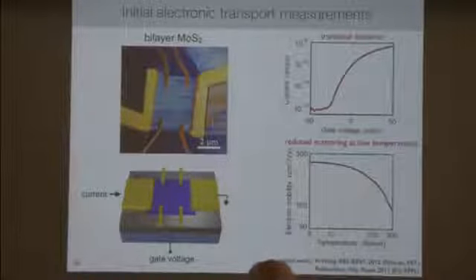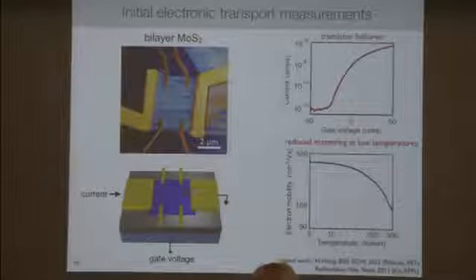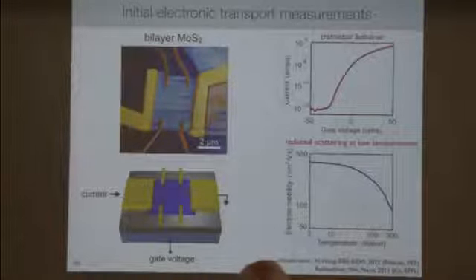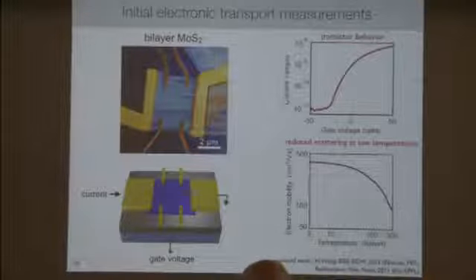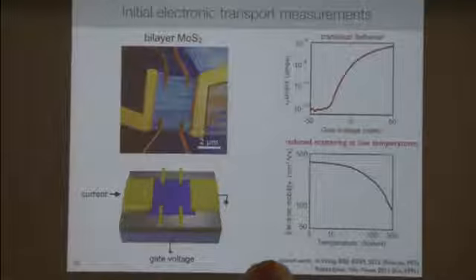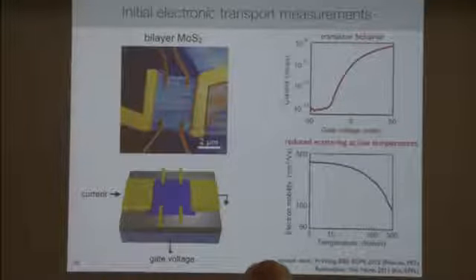So we've done some initial measurements on these materials. So here's a bilayer of molybdenum disulfide that we've contacted with gold, and we can measure then current flowing through the molybdenum disulfide as a function of voltage that we apply to the silicon substrate that this thing is sitting on. And for example, consistent with other groups around the world who are working on these things, we see that this material does in fact behave like a transistor. A transistor is just an electrical on-off switch. When it's on, there's a large current passing through the device, and when it's turned off, the current has been reduced to just a trickle.